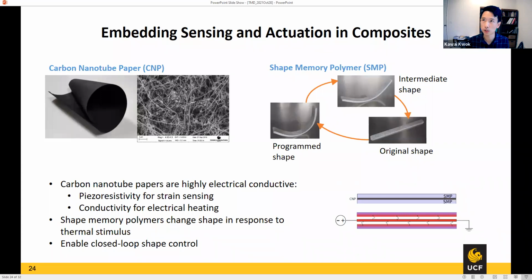In order to have actuation and sensing together, we have to combine the capabilities of both. What we are getting from the carbon nanotube is piezoresistivity, which really means that if you apply a strain on the carbon nanotube, you see some change in resistance. If you put a voltage and measure that resistance, it relates to the strain, so that is a strain sensor. But we also use it as a heater when we incorporate it with the shape memory polymer, because all the shape change is thermally activated. So we can achieve both purposes with the composite with the carbon nanotube. This is a simple structure that we came up with. We laminate the carbon nanotube paper between two SMP layers, and we can connect that electrically to the CNT, which provides the heating and also the strain sensing.